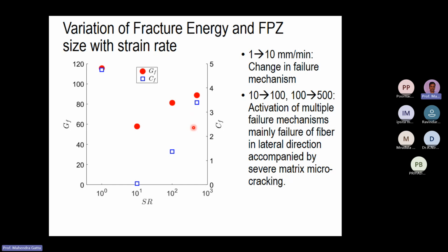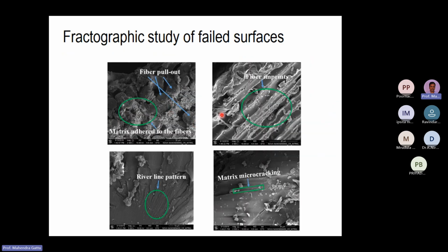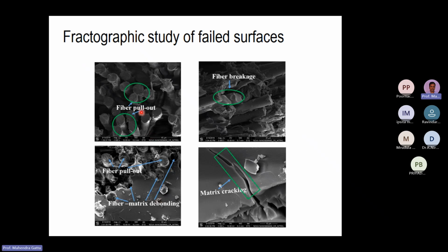So we wrote our first paper using this data and basing on the SEM images for different loading rate. So we see that SEM images, which was done in our metallurgy laboratory. So we looked at the failure surface and see some fibers, fiber pullout, the fiber imprints, matrix microcracking, that is cracking in the epoxy resin, and riverline patterns in the epoxy resin. When we found out fiber breakage, that is fiber actually breaking out at this loading rate.